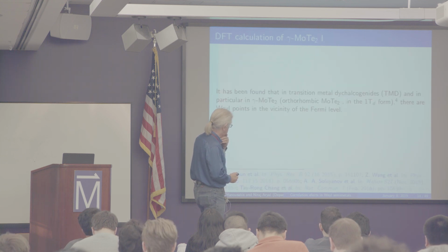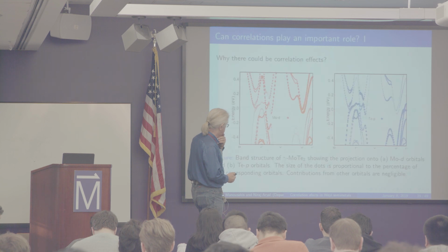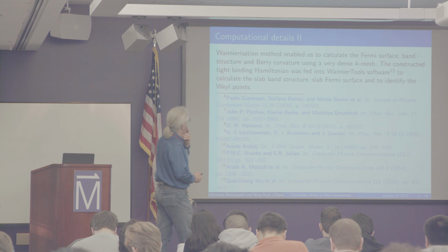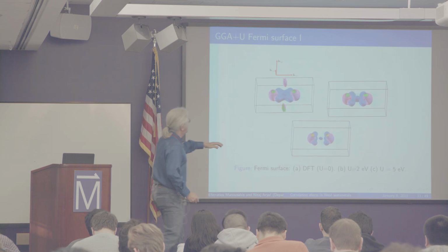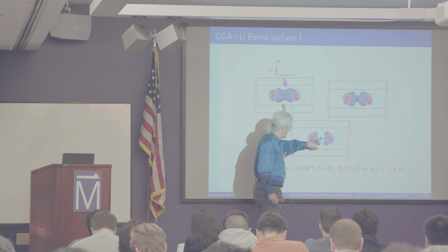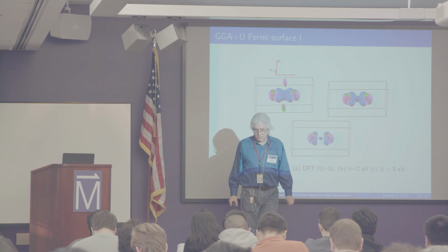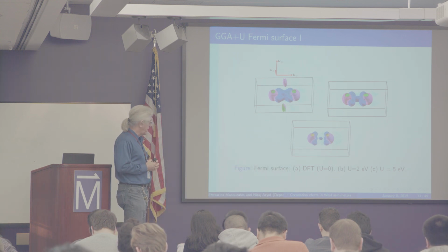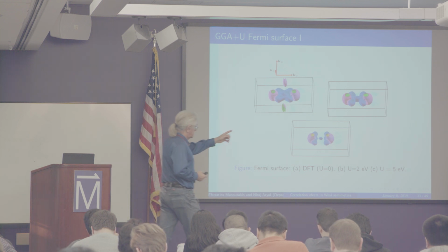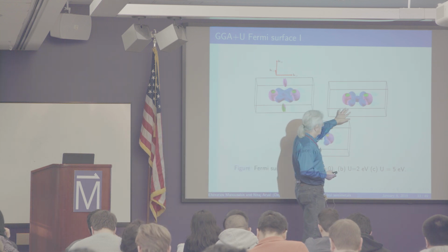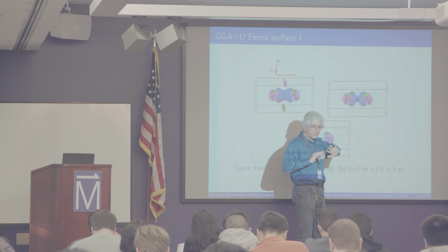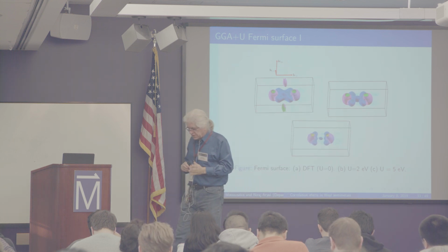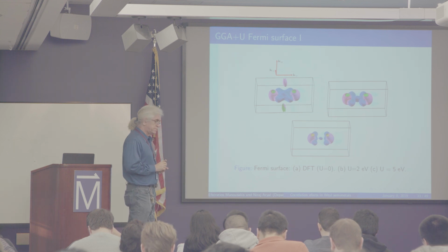Here, U equal to 5 has a disconnected Fermi surface. The ears separate themselves from the core, the gamma point hole pocket. And because of the polarization dependence, this looks closer to ARPES. So if you want to be faithful to both worlds, I will accept some moderate value of U.